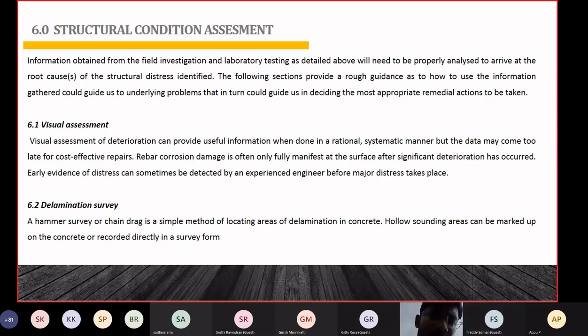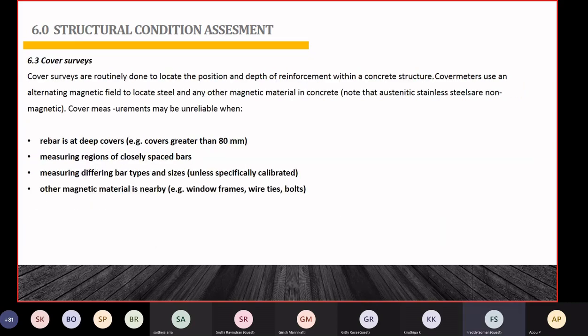Then the delamination survey. Whenever we go for an investigation, we have to do a delamination survey also. It's a very easy test actually. With a small hammer, we knock on the surface. If a hollow sound comes, that means the area is delaminated. We randomly select some area for the delamination survey, maybe an area of 2 meters by 2 meters, and we will give the report. If some area is delaminated, then we extend the survey to incorporate more area. It's an easy test actually. From the hollow sound, we can identify whether the area is delaminated or not.